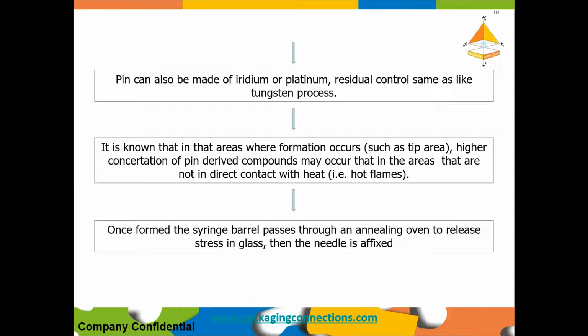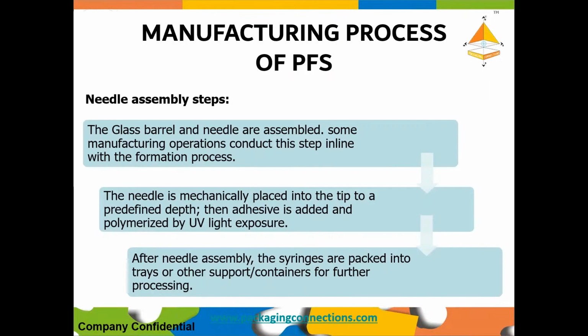Once formed, the syringe barrel has to go through the annealing oven to release all the stress in the glass, and then the needle is fixed. And then the needle assembly process. The needle is basically mechanically placed onto the tip. An adhesive is applied, which is cured with the help of UV light. The reason to use UV light exposure is very, very important: it needs to achieve the adhesion almost instantly because the needle has to remain straight. If the needle is fixed at an angle, then it could create problems in many other processes. It has to be straight.